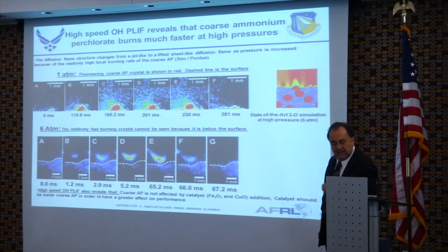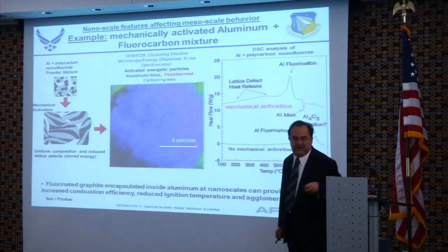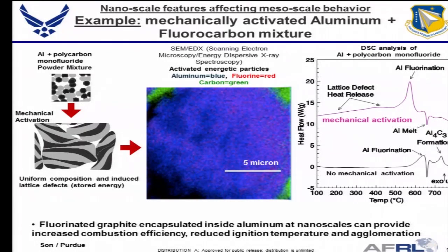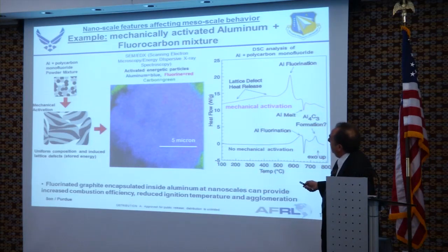available for this stuff. Now, the second one is about how nanoscale features can affect mesoscale behavior. Aluminum is used in propellants for the high energy content and also for instability suppression. But it ignites at very high temperatures, around 2,000 degrees Celsius. Because of that, it creates incomplete combustion. The particles stick together, they agglomerate, and they create slag and all kinds of problems in solid rocket motors. But if you can mix that aluminum with polycarbon monofluoride, then you will reduce that ignition temperature to around 650 degrees Celsius. But if you do a mechanical activation, okay, if you can induce some lattice defects into this,